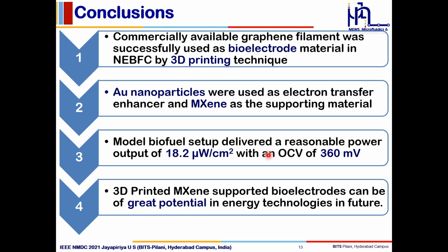Hence, we conclude that commercially available graphene filament was used as a bioelectrode material for the non-enzymatic biofuel cell with the help of the FDM 3D printing technique. Gold nanoparticles were used as an electron transfer enhancer, and the 2D material MXene was used as a supporting material for deposition of gold nanoparticles. A model biofuel cell setup gave a power of 18.2 microwatts per centimeter square with an open circuit voltage of 360 millivolts. Hence, 3D printed MXene supported bioelectrodes could be of great potential in the energy technologies of the future.